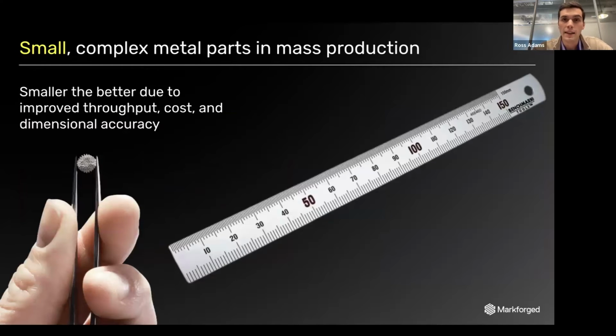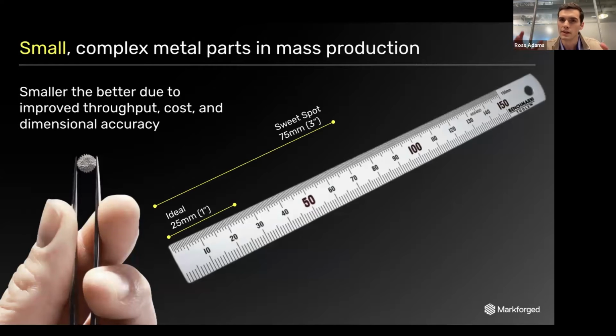So starting with small, I typically say the smaller the better. And the reason there is that we get higher throughput. With the higher throughput, the cost per part becomes improved. And even the dimensional accuracy gets better with smaller parts, because we shrink about 20% during the sintering, so basically the larger the part, the larger the shrink. And we get better accuracies with the smaller components. So to get more definitive there, the ideal parts are about 25 millimeters or 1 inch or less in the longest direction of the component. We love these parts. These are really good fits for the technology. You can get really high throughput. The cost effectiveness is very strong. We get really tight tolerances. Now we can go bigger, and I'd say about 75 millimeters or less is the sweet spot. When we're below that, we definitely have something here that we can go and evaluate and have high confidence that we have the right technology fit for that type of geometry.